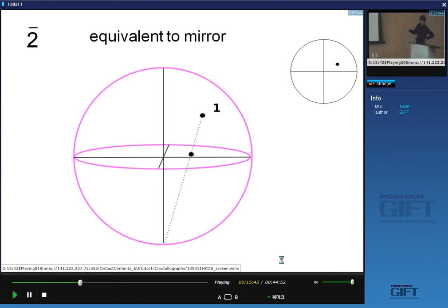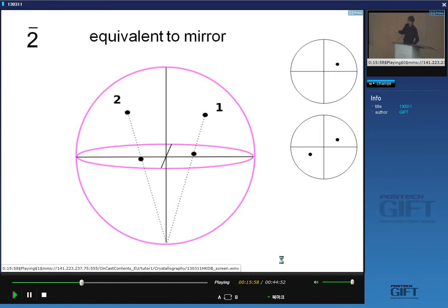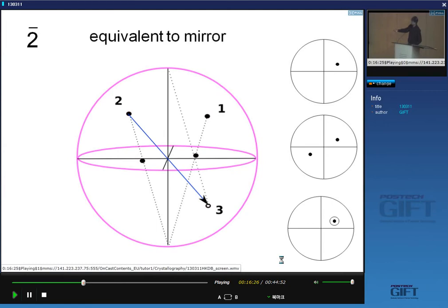And in order to plot it onto a two-dimensional equatorial plane, we project it through the South Pole, if that point happens to lie in the Northern Hemisphere. Now I do a rotation, so that point on the equatorial plane comes over here. If I do a rotation of 180 degrees, and I project this point again through the South Pole, then I obtain another point on the stereographic projection, which is the consequence of 180 degrees about this axis. Okay. And now I do the operation which is identified with this bar over here, which is inversion through the center, and that's the point three.